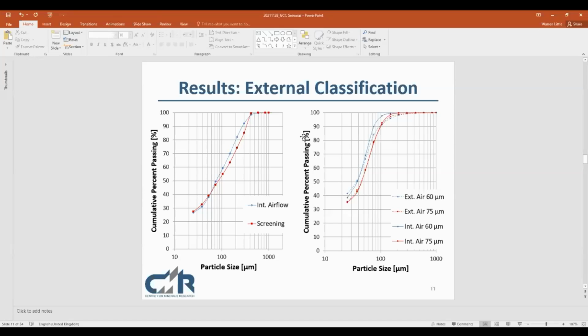On the right hand side we have the comparison between the external and internal air products. At the finest grind, the P80 of 60 microns, we see quite a deviation between the external and internal air classification products. The external air product has a significantly coarser component in the tail. Where the internal air classification product has pretty much 0% plus 150 microns, the external air classifier product has about 5%. At the target of 75 micron P80, both the internal and external air classification PSDs are very similar.